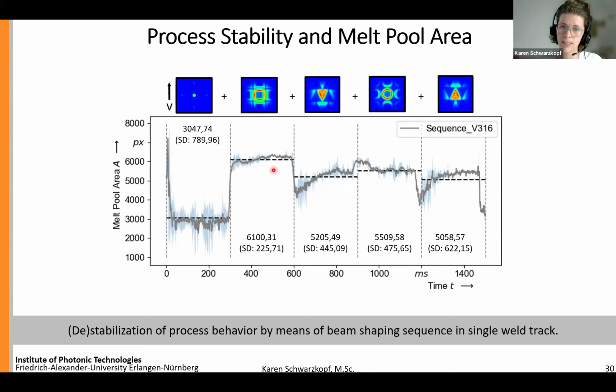And what is now interesting to see is that we get the highest melt pool area for the square. And this is also really correlating with the highest powder catchment efficiency here for the square, followed by the ring. And what is now interesting to see is that we do have a decrease of the melt pool area when we're switching, especially from the square and the ring intensity distribution towards the triangular shapes.